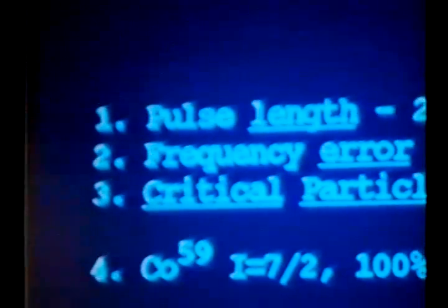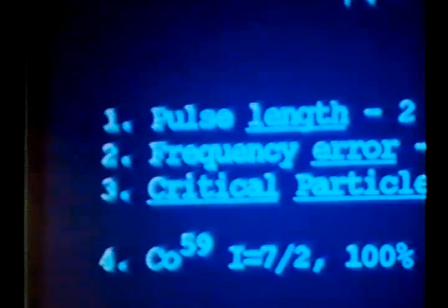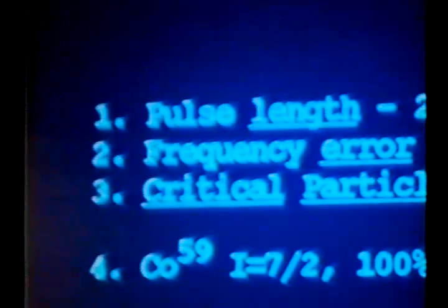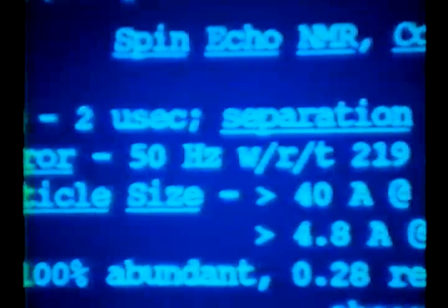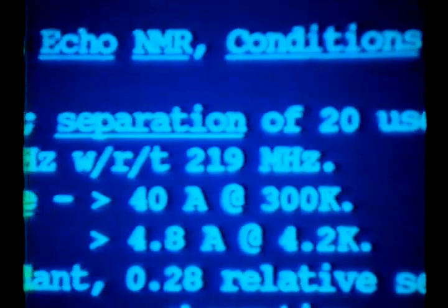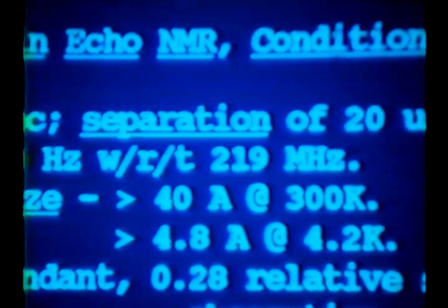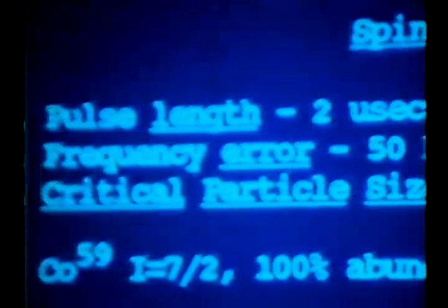And for the chemists that are here, this is not the normal spin echo NMR that we hear about and read about in the literature. This is not the same thing. Technically, we would probably call it spin echo ferromagnetic resonance, spin echo FMR. The reason is that this experiment is done at zero external magnetic field. There's no magnet. You're relying on the very strong magnetic field of the cobalt particles to do this experiment.